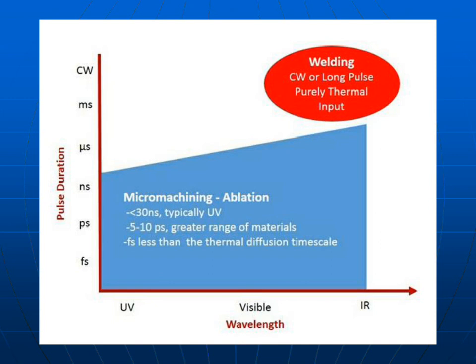If you come down to the shorter pulse length, getting into the microsecond and even nanosecond, picosecond, and femtosecond arena, you'll see that even in the infrared, these lasers can be used for micromachining. And as you travel further on the x-axis towards the origin, you go further into the UV. And as you go further into the UV, with a shorter pulse length, this becomes the optimal condition for doing micromachining and material removal with very clean results. You'll also notice that in the upper left-hand corner, there's really nothing going on. And that's because there really aren't very many uses, or no uses that I'm familiar with, for long pulse length or CW UV lasers. So typically they're not really used in an industrial environment, although there's no reason why those lasers can't be made.